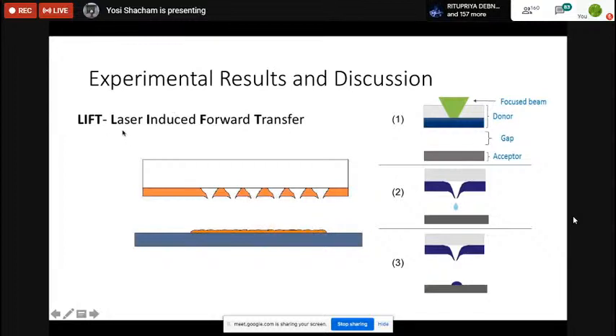Because we have a laser, the substrate you're taking is called a donor. And from the donor, you are generating a metal drop. This is like an inkjet printer, but instead of having a cassette, we have a substrate of glass with gold. And we put drop, drop, drop, drop. We can put more than 100,000 drops per second. And you can take many beams of the laser, so you can work very, very fast. And this is a commercial product.